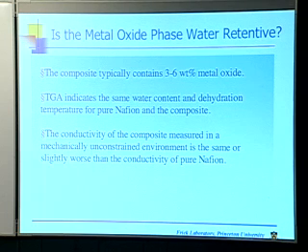Metal oxides might be a little acidic, but they're not going to be as acidic as that. And so one might guess, correctly, it turns out, that when you add a metal oxide, if you did anything, you would withdraw protons from the system. That is, the acid's going to protonate the metal oxide, and now those protons aren't available for transport. And so that doesn't make a lot of sense. And even if it went some other way, there wasn't enough material here to really explain that.